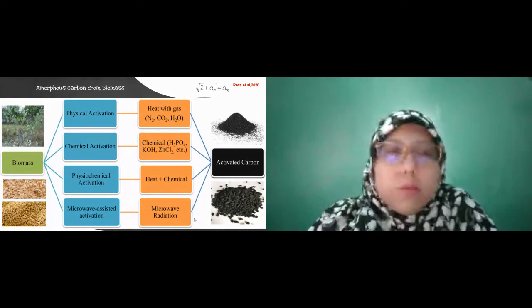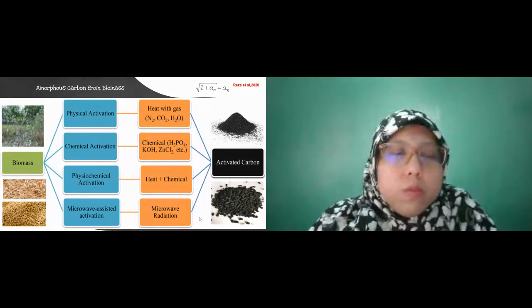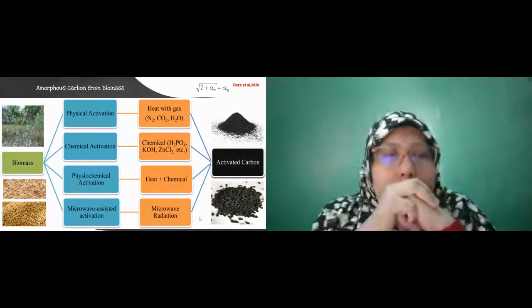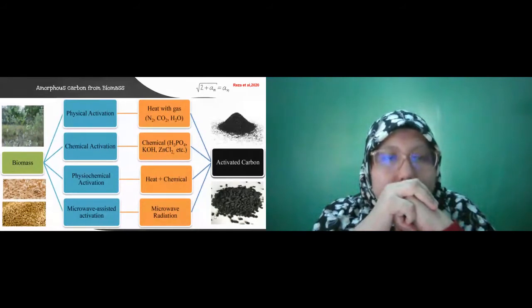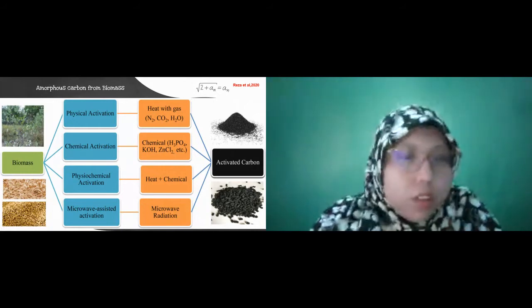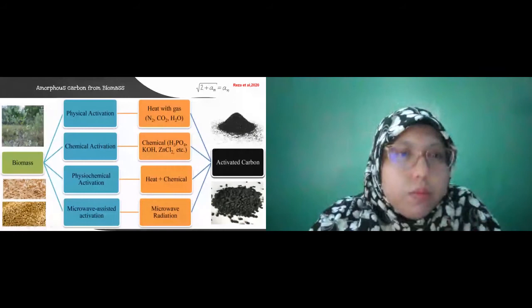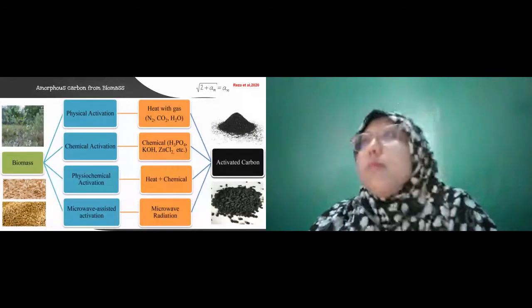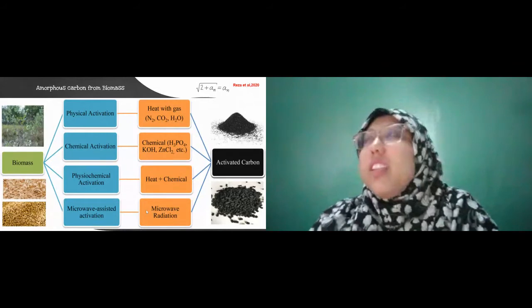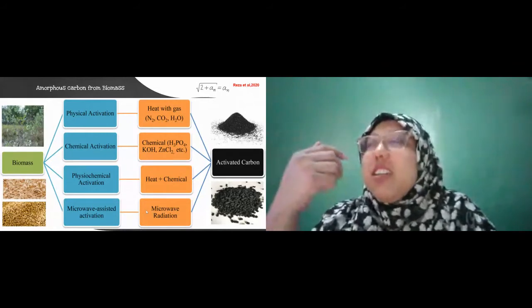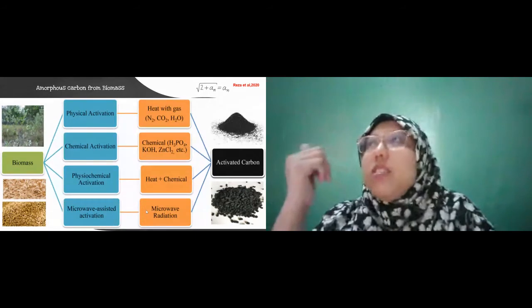Slow pyrolysis uses a slow temperature rate, and that one also works as an adsorptive material. Also fast pyrolysis is there, where we keep the temperature above 500 to 800, 900. We also can activate a biomass by chemical activation, where we use potassium hydroxide, any salt or acid or base, all can work. We are also currently using the two-step method, like physiochemical activation. There we do pyrolysis and chemical activation both together to ensure that the surface area has proper pores and is very good for absorption.